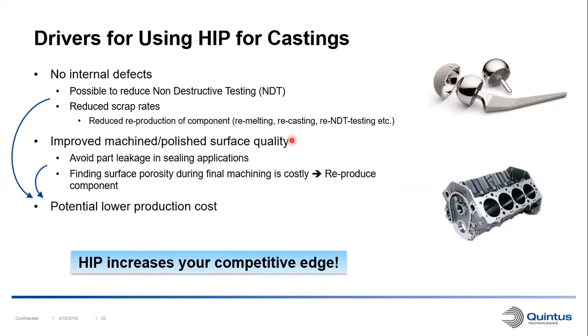In the same way, if we don't have any porosity that can be outside of the spec, we can also reduce the scrap rates for our castings. And this is very good since we don't have to remelt, recast, and re-NDT components. The improved quality of machined and polished surfaces makes it possible to avoid part leakage in sealing applications. And also, it's very annoying to find surface porosity during final machining of a part, where all that value-adding work that you put into the component at that point is just flushed down the drain when you have to reproduce that component. So all of these points make a potential to lower the production cost in the casting process chain.